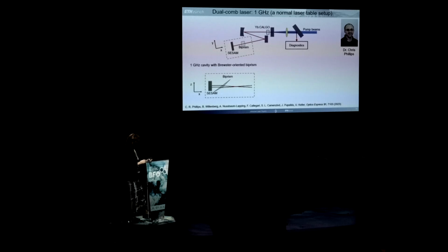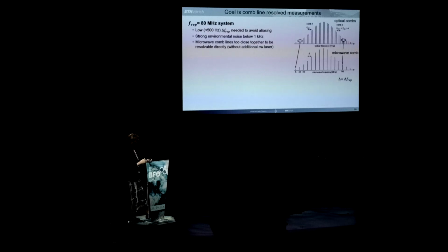And then, with this ytterbium CALGO laser, we then demonstrated, next, 3 watt of average power with 78 femtosecond at 1.05 micrometer at 1 gigahertz. And you can then, again, by translating this biprism, tune it. So these are powerful, ultra-stable frequency combs.